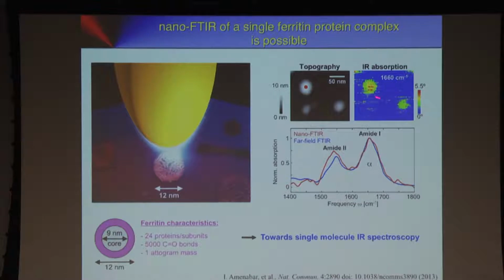We see a strong absorption contrast for these two particles, but not for this particle here. So we know these are protein, and this particle obviously does not absorb at this frequency, so it's obviously no protein. If you measure carefully, you see this particle is smaller. Obviously it is not an intact protein complex, but just the core. This fits very nicely. I have another image that we took some scans before, and this particle was absorbing. The particle became smaller, so either we heated it up and destroyed it, or we disassembled it by scanning, and then the contrast vanished. In principle, we measure the protein functionalization of a single particle with only a diameter of 12 nanometers and 2.5 nanometer thickness.